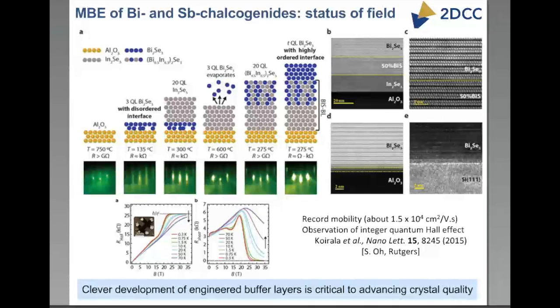And not only that, they have the highest mobilities I know of, at least in bismuth selenide thin films, something like 15,000 or so centimeters squared per volt second at low temperatures, and they observe an integer quantum Hall effect. So this just gives you a sense of the kind of strategies that exist in the MBE world, and clever development of engineered buffer layers is certainly critical to advancing the crystal quality.